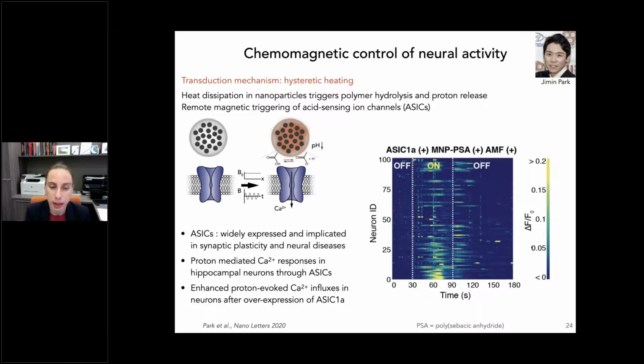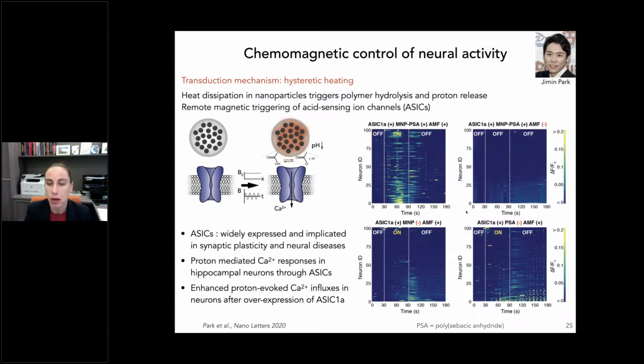And then we can apply this magnetic control of pH to a group of neurons, in this case, that are expressing these acid-sensing ion channels. We will see that only when our polymersomes have the magnetic particles, and only when we apply the magnetic field, will we see calcium influx, which is a proxy for neural excitation. But if our polymersomes are empty, or don't have particles, or if we don't apply a magnetic field, or if our neurons are not sensitive to local change of pH, we don't see a significant increase. I bring your attention to these control experiments where we do have a little bit of response to heat, because the concentrations of particles here are actually quite substantial, unlike in the liposome work where you just need a few particles.